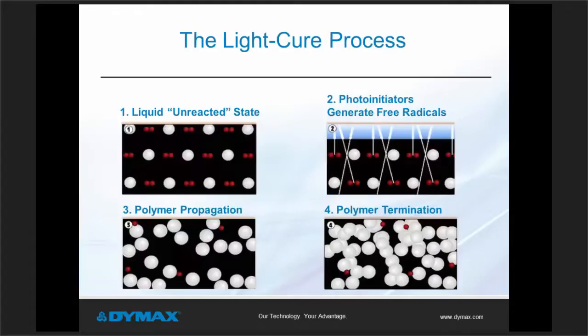So here's an illustration to show what actually is happening. Each quadrant is labeled 1 through 4, as you can see. In box 1, the light curable material is in an unreacted state. In box 2, the curing process is beginning. This is when the photoinitiator in the material is exposed to the energy source of the proper spectral output. It excites and fragments photoinitiators and results in generation of free radicals. In box 3, in the lower left, the free radicals actually begin to attach themselves to the acrylates that make up the light curable material. This results in polymeric chain radicals. The process is repeated until all the radicals are attached, and there's polymer termination, which is basically cured material, and that's what you see in box 4.